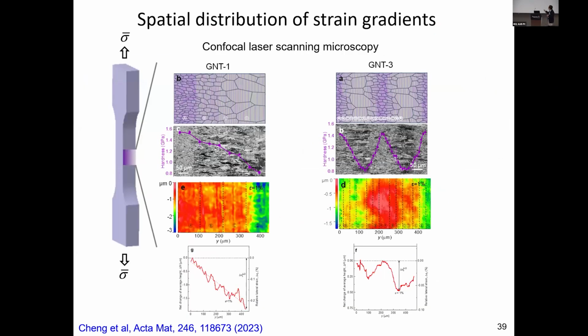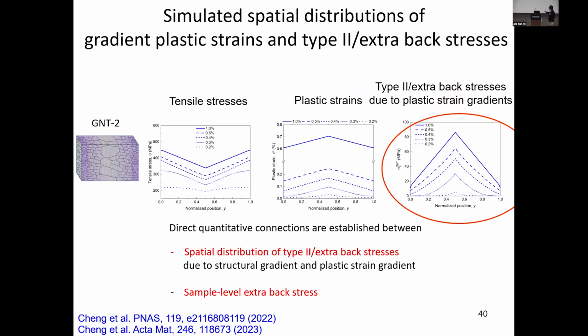And this study, coupled with spatial mapping of the strain within the cross section, really enables us to quantitatively evaluate these two types of strengthening effect. And then we can predict the non-uniform distribution of the stress within the sample and that evolves with the load, and also partition this